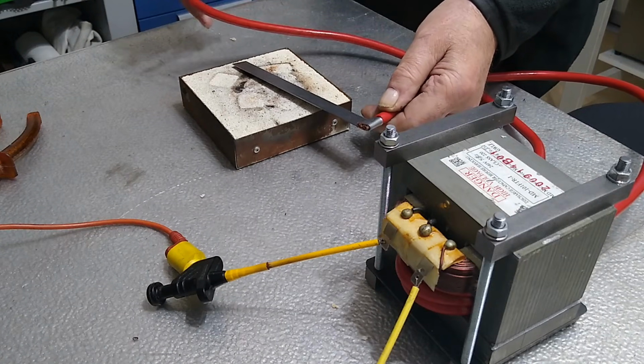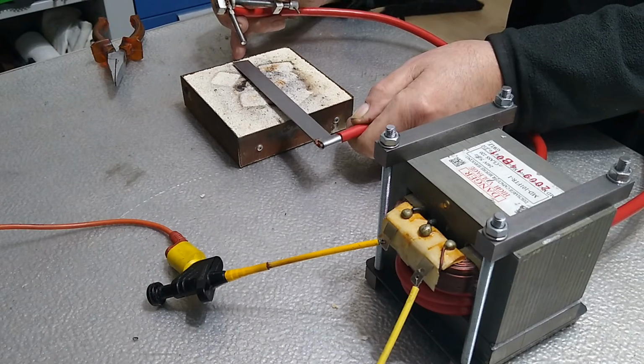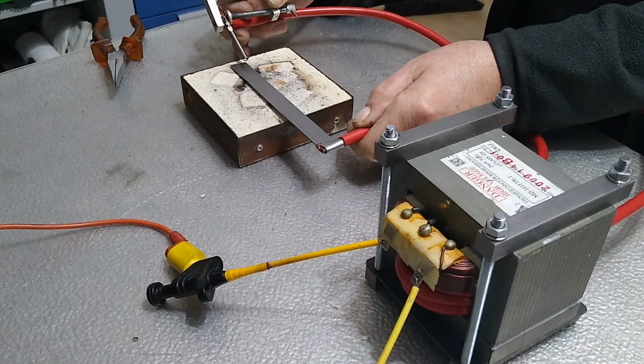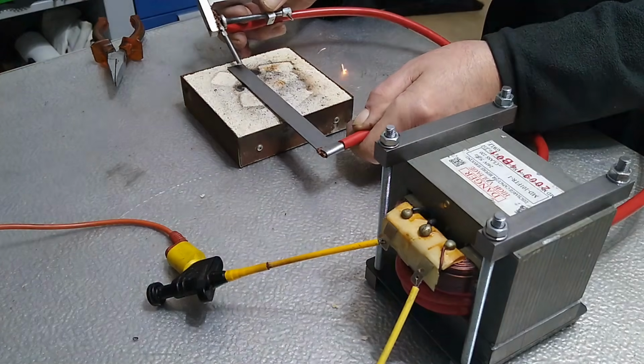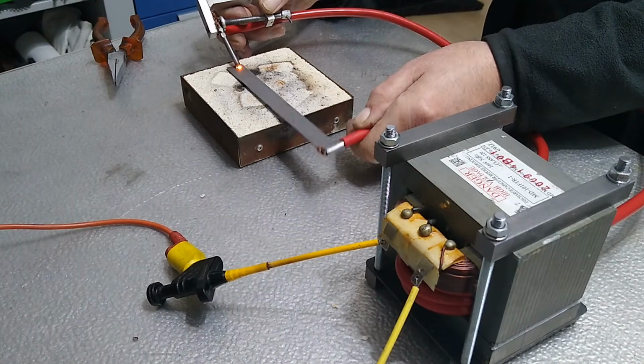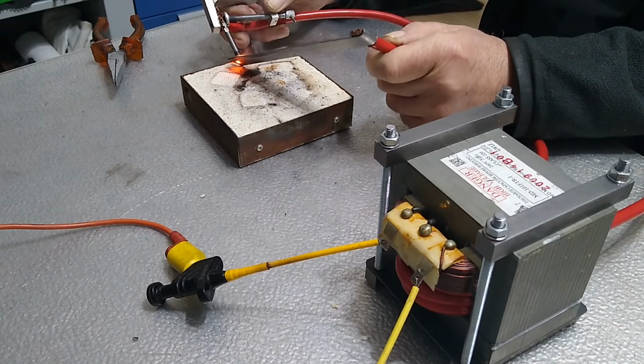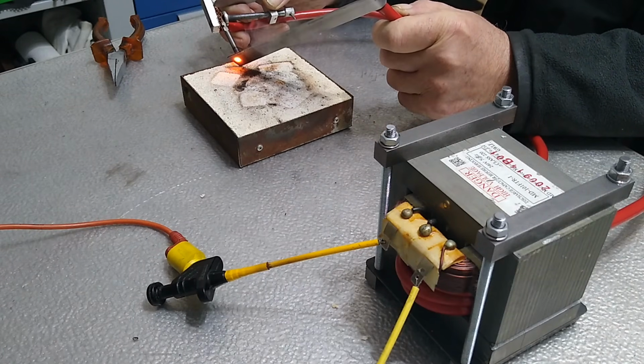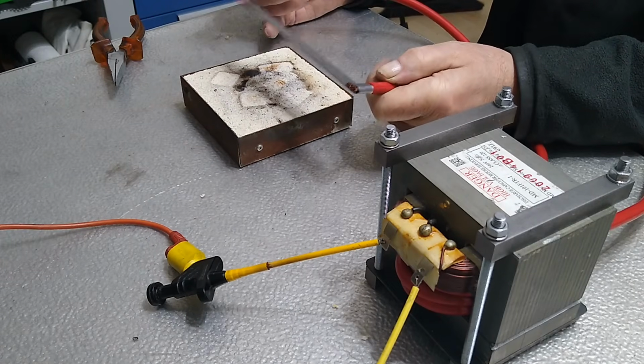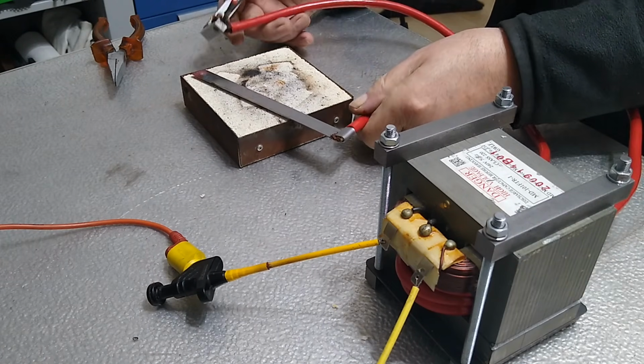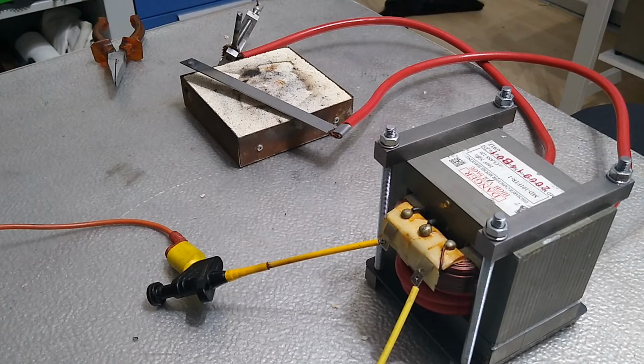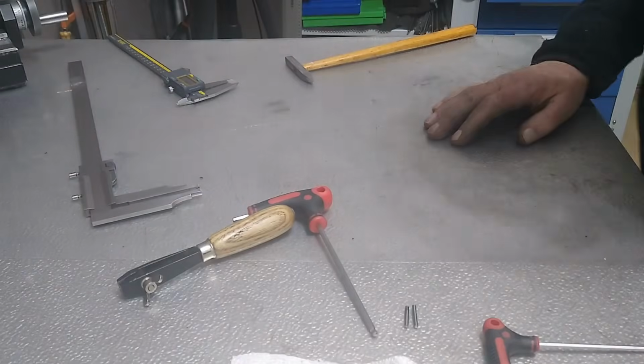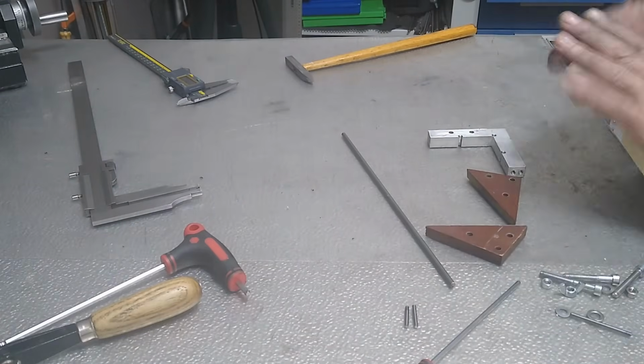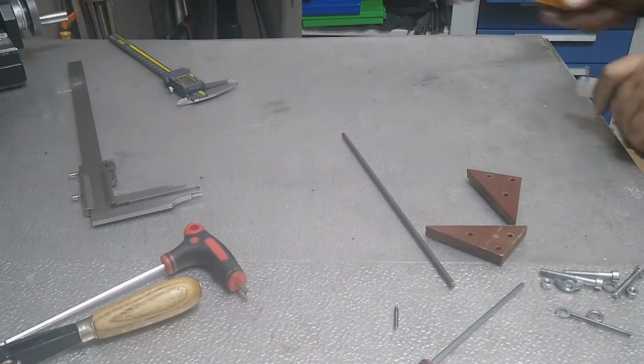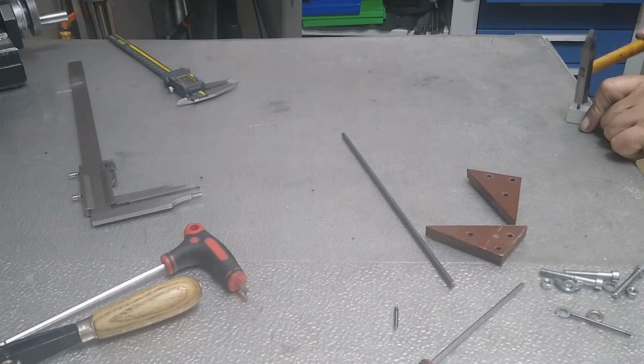On YouTube you will often hear claims of more than 1000 amps from these transformers. Yes, that is possible, but only as a short-circuit current. The secondary winding, and the transformer itself, will not survive that for long. At 1000 amps the primary usually pulls well over 2 kilowatts, which is rather unhealthy for a transformer rated at 900 watts. Realistically, somewhere between 200 and 300 amps on the secondary side is about the maximum you can extract from these units without inviting unpleasant smoke signals.